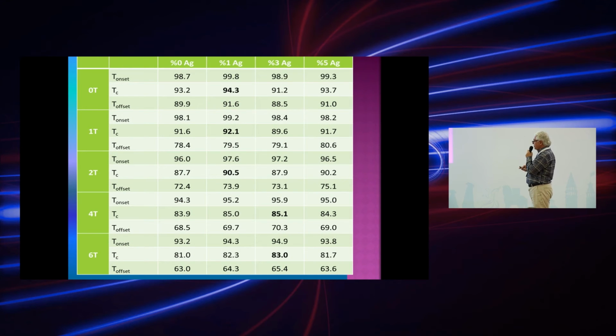Then by looking at these pictures, we have deduced our TC onset, TC offset, and the critical field from the figures. As you see, the TC onset doesn't change so much, look here, for all applied magnetic fields. But I would like to put emphasis here: the TC offset temperature is changing drastically by increasing magnetic field in comparison to the onset one. This is the part to be investigated.